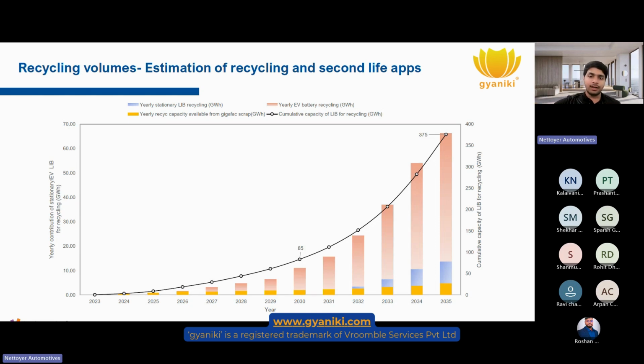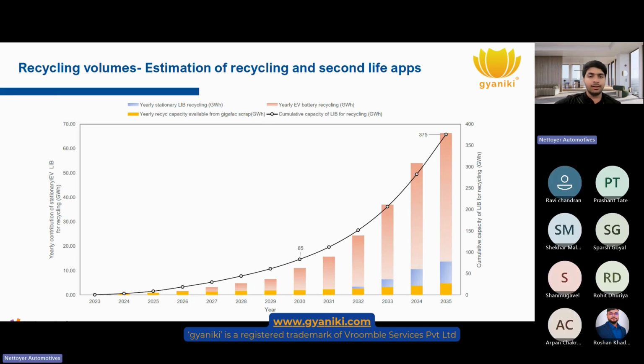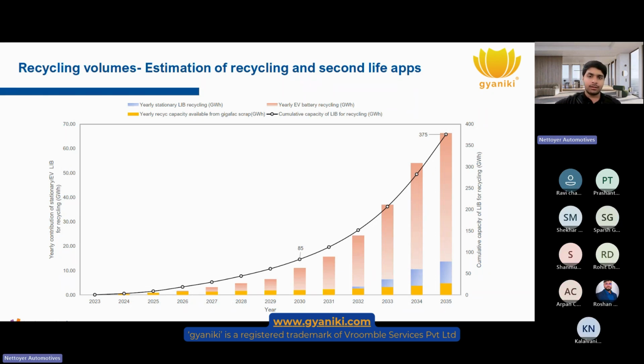When we go just below that, we have lithium-ion cells, 36650 or 18650, which are utilized by electric vehicles. There are other standards of cells also, but the main chemistry remains the same. 4% will be lithium, 7% would be nickel, about 22% would be cobalt and graphite respectively, and then other metals or metal salts as well. Then if you go just below that, apart from A grade cells, we have B grade cells, which have a discharging capability of 95, 90% only, or even below that. Those cells are utilized in rechargeable energy storage systems for renewables.